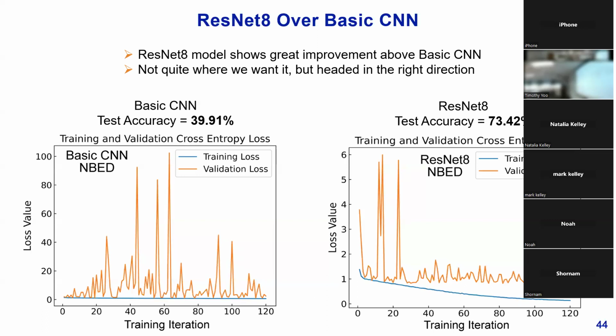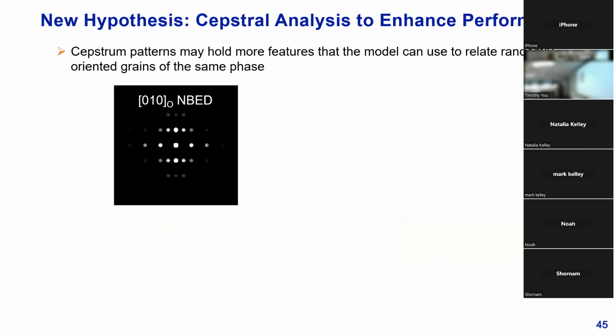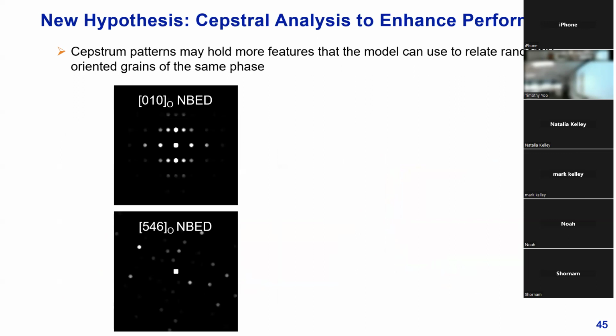And so at this point, honestly, I'm kind of stuck. And of course, when that happens, you have to try to reassess your initial hypothesis. Okay, so I'm going to try to take you guys through some of my thought process here. This is an example of a simulated pattern of 010 oriented orthorhombic. My idea was I wanted this model to essentially understand that this was the same phase as this, which is a much higher index zone axis of the orthorhombic phase, just 5, 4, 6. Somehow in my head, I thought, okay, I can make this model learn that this is the same phase as this.